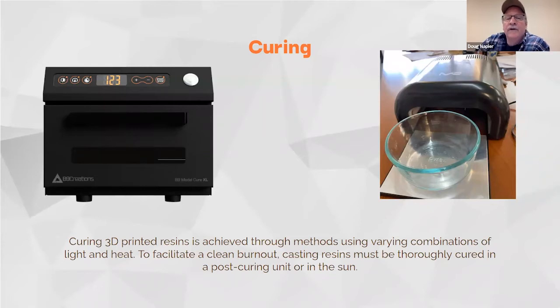And again, when you're curing your pieces, the time is all based on the thickness of the piece. So if you've got a piece that's real thick, even in my model curing unit that I use now, I'll still cure it for half an hour. Even though it only goes up to 9 minutes, I'll go through that 9 minute cycle three or four or five times just to make sure that it's completely cured.